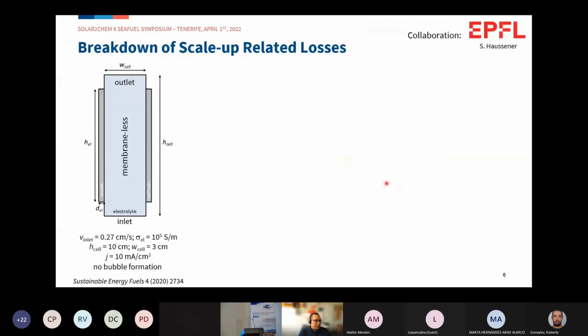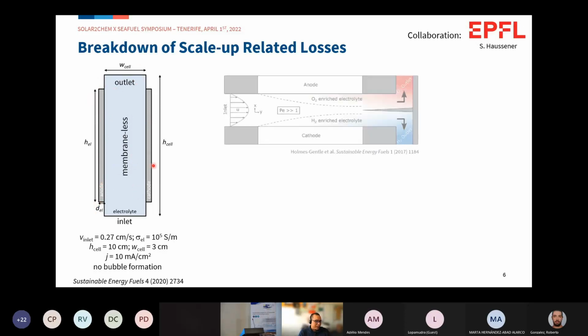To understand that further, we collaborated with Sophia and developed a simple two-dimensional model. Since bismuth vanadate is not the problem, we take it out of the equation and replace it with just the anode and the cathode. We used a simple membraneless configuration reported in the literature, where hydrodynamic control of the electrolyte is used to ensure product separation.